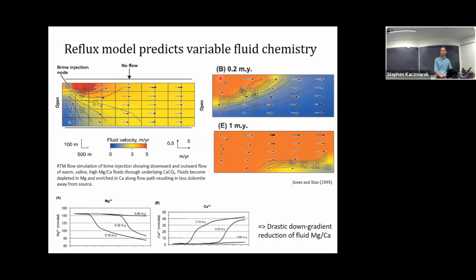The red is a high degree of dolomite, and blue is the limestone. You can see after 0.2 million years, there's a gradient from fully dolomitized to partially dolomitized into the undolomitized limestone. And if you let this model run long enough, you just dolomitize the whole section. This has been used as supporting evidence for this model.